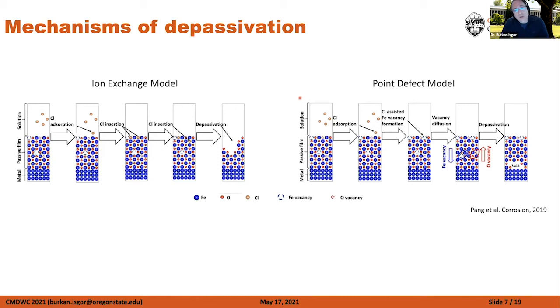When we talk about how chloride-induced depassivation occurs, there are different models that have been used to explain that process. I picked here two of those. There are more than two, but I picked two because they capture more or less the big messages of different types of models. One is something we can classify under the ion exchange model, where chloride can actually be absorbed and diffused into the passive film. Some people explain after diffusion how the breakdown occurs in a different way, and the others say that maybe it actually destroys the passive film.